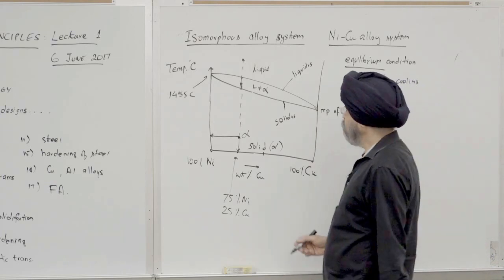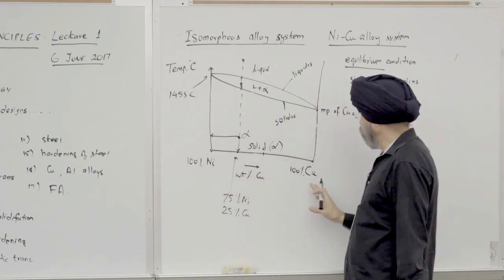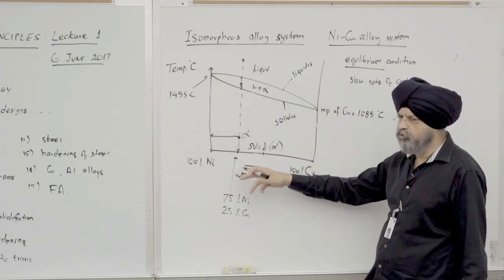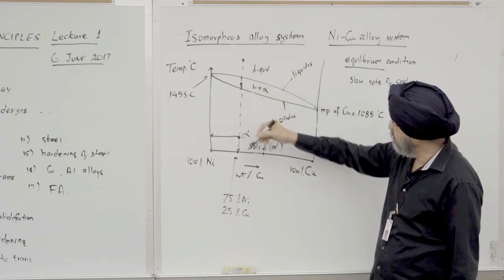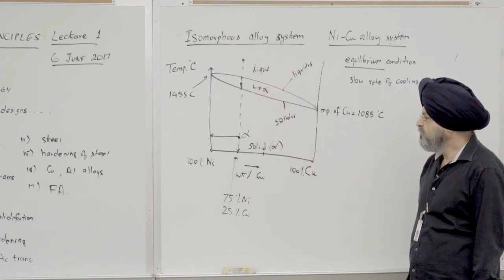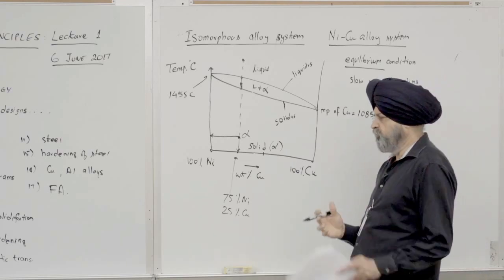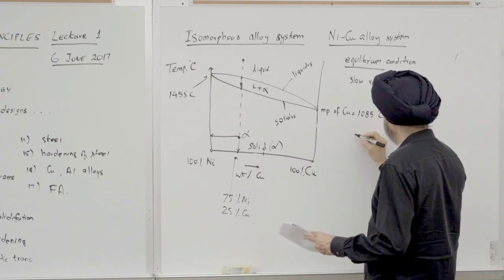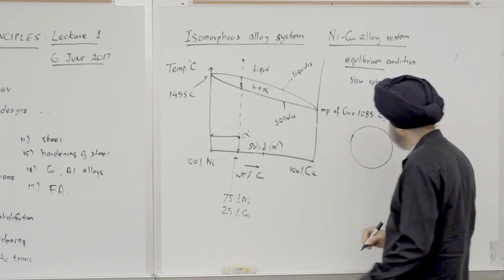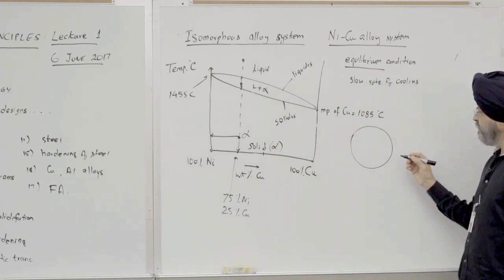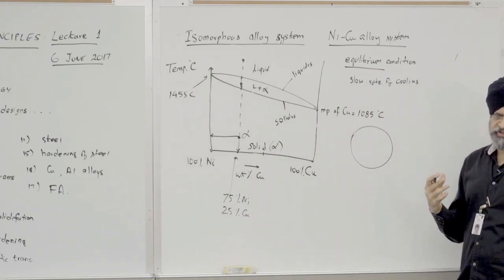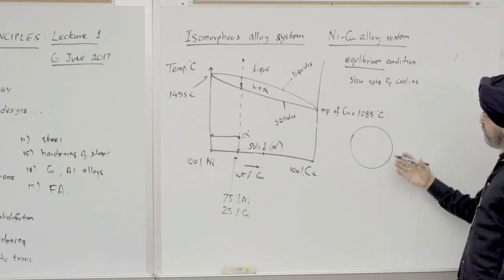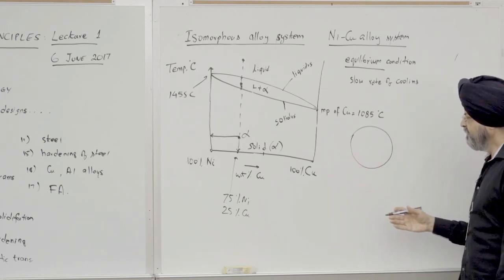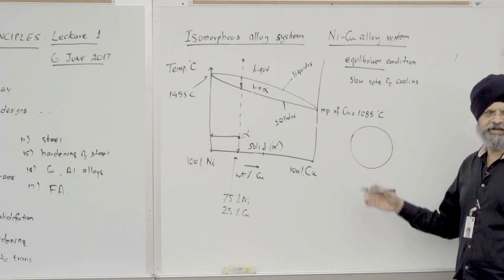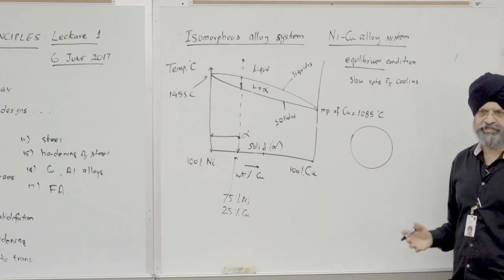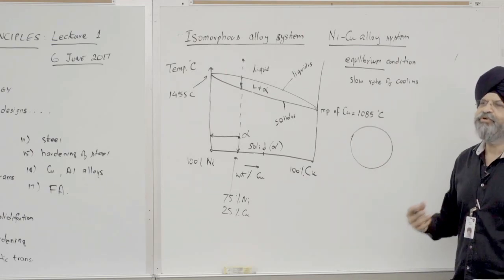So let's suppose we took nickel and copper, we mixed them up, we alloyed them, and we cooled it to room temperature. So let's look at the microstructure. We have this piece of this alloy, and the way we look at the microstructure is we cut the alloy. Actually, we give it to Larry. Larry cuts the alloy, he polishes it, then he etches it. And then what do you see?